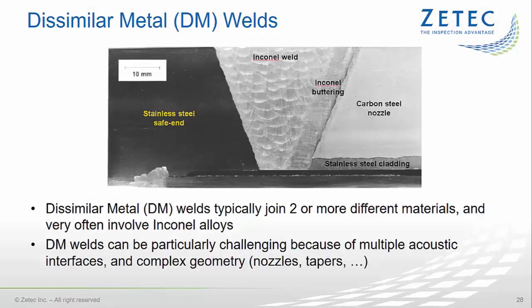Dissimilar metal, or DM welds, typically join two or more different materials and mostly involve Inconel alloys. These welds are often used to connect clad carbon steel vessels to stainless steel piping. Dissimilar metal welds are a very challenging configuration for UT examination due to the various propagation issues in austenitic structures, the presence of multiple acoustic interfaces, and the sometimes very complex geometry.